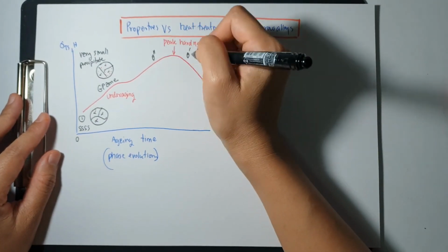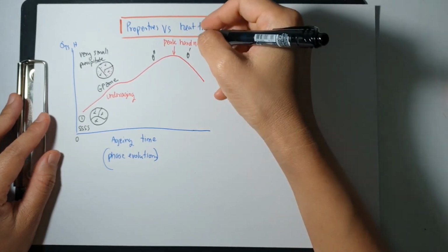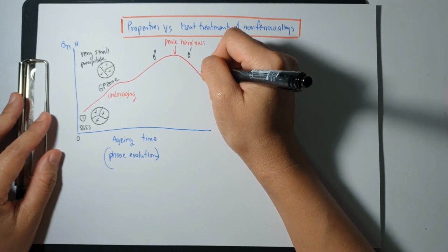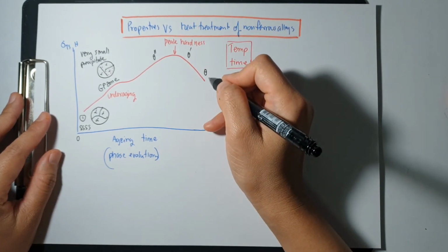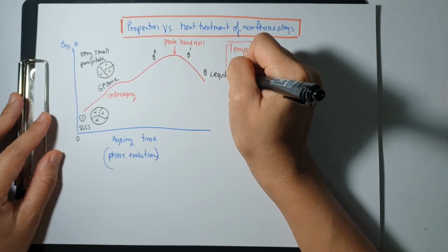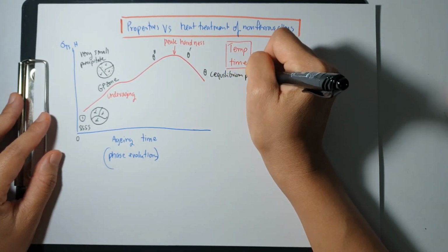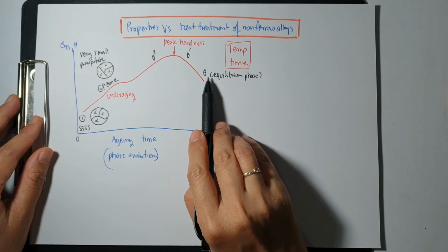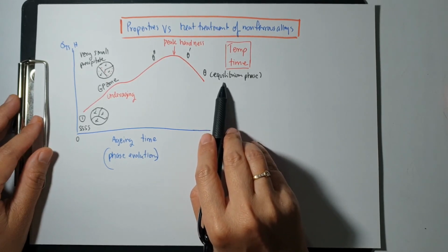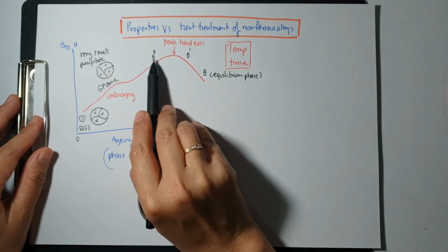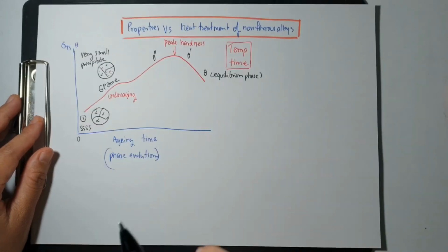Okay, as I write down over here, these two phases are not the equilibrium phase, which is down here. As you remember on the last slide, the equilibrium phase of theta phase is very coarse and not coherent to the matrix. So what we need is the theta double prime and the theta prime.